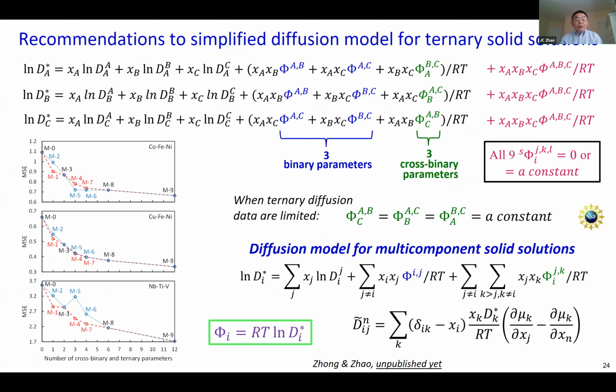So now, if you only do that, then the ternary interdiffusion coefficient becomes really simple. This is carried over from the binary, right? For the three binary systems, A, B is equal, as I mentioned; A, C, this is equal; B, C, this is equal, right? And three parameters, and then three cross-binary parameters.